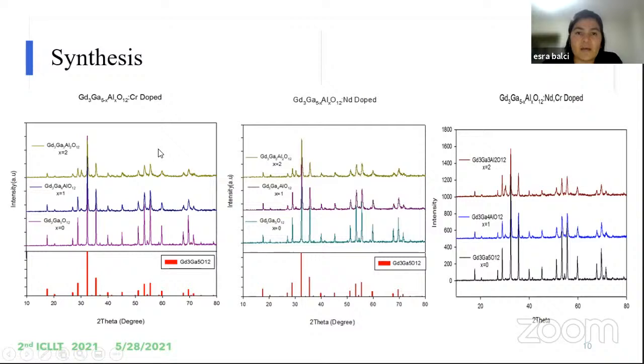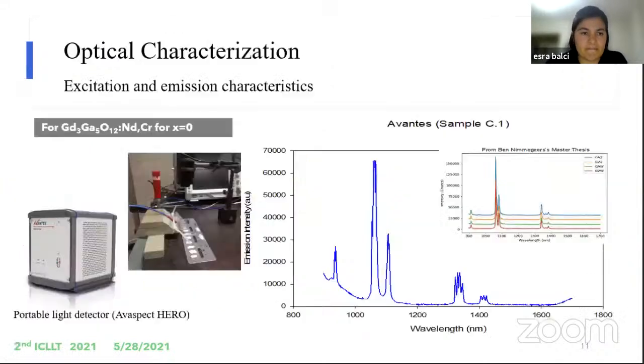These are the XRD graphs of our material for chromium doped, neodymium doped, and both neodymium and chromium doped. As you can see, we also compare X0, X1, and X2. If you see in here, some new peak is created for X2 because our material is changing and it's normal to change our peaks. It's almost 30 degrees on the 2 theta axis.